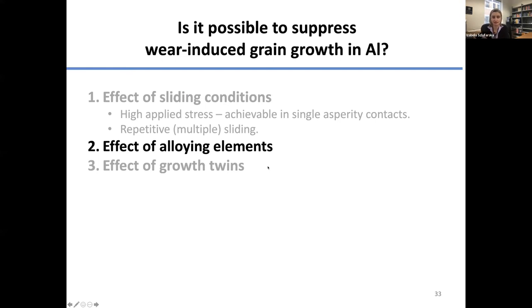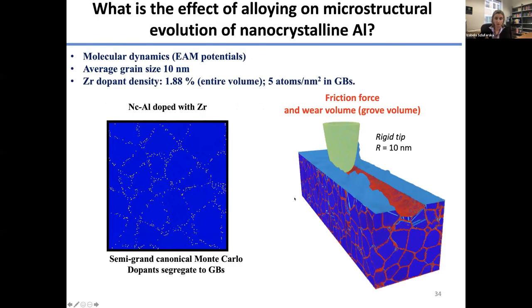Okay, so the last part of the story I'll have time to tell you about is to look at the effects of alloying elements. Again, we were interested in how to control the microstructure during wear of nanocrystalline ultrafine grain aluminum. In this case, we look at our simulations. So these are molecular dynamics simulations, and we have samples here of nanocrystalline aluminum, so it's a smaller grain size, that are either pure nanocrystalline aluminum, or aluminum doped with zirconium. You can see this yellow point here, this is zirconium. The reason we chose zirconium is because it segregates to grain boundaries in aluminum, and we wanted to understand the role of grain boundary dopants on wear.